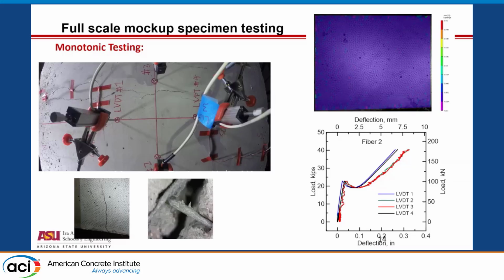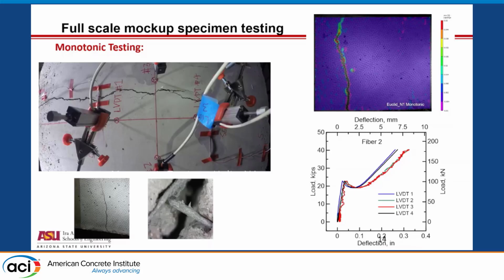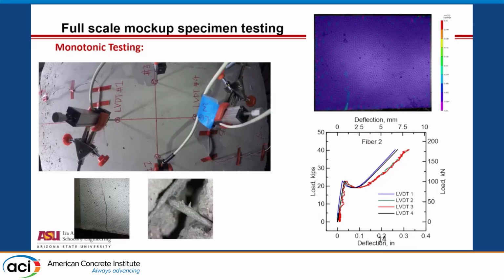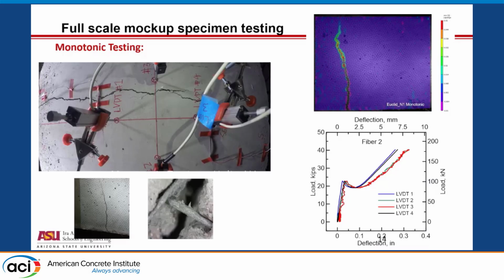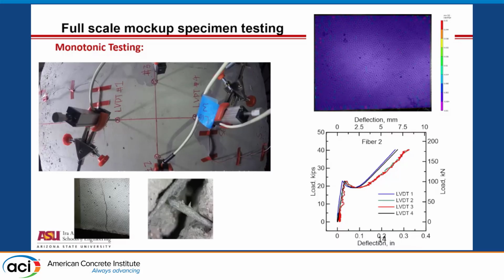The sample is loaded to more than about 2.5 times the design capacity, assuming that the train is filled to capacity. And then once the concrete cracks, it just drops, but the load can still be carried through the rail, through the entire system, and the rail now is carrying a lot of the load. So this is a composite total effect of the load and the concrete phase. 4 LVDTs almost measuring the same response.